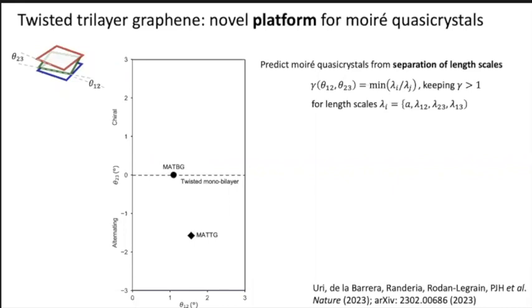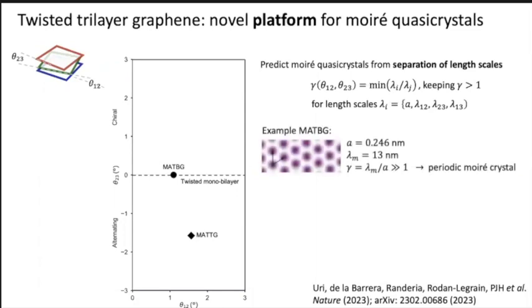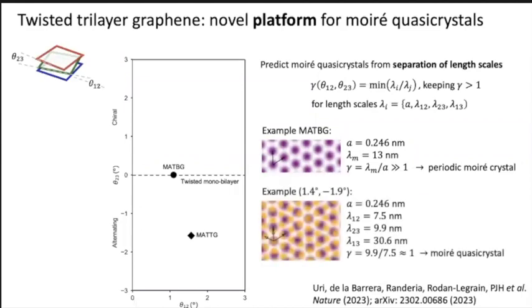And this is for length scales which are the atomic length scale and the Moiré length scales given by the Moiré pattern between layers 1 and 2, 2 and 3, and 1 and 3. So for example, in magic angle twisted bilayer graphene, the atomic lattice scale is 2 angstroms. The Moiré wavelength is 13 nanometers. Gamma, lambda_m over a, is much, much greater than one. In that case, when there's a large separation of length scales, you get actually a periodic Moiré crystal, okay? In the case that I just showed you, 1.4 and minus 1.9 degrees, these are the relevant length scales. This parameter gamma, the minimum ratio of length scales, is actually close to one, okay? Under those conditions, you get a Moiré quasi crystal.